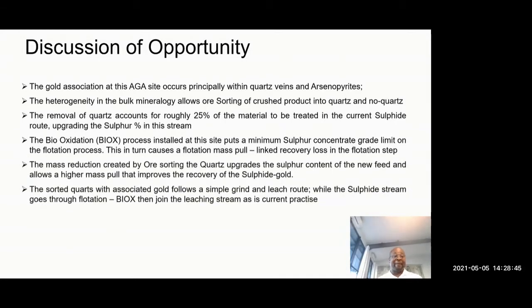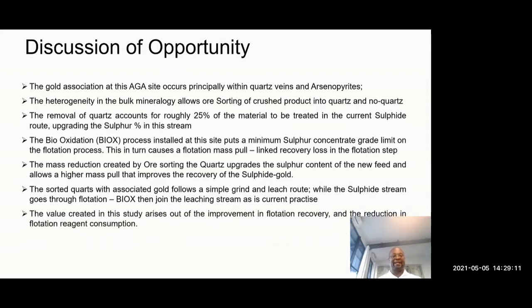So what are we doing? The mass reduction created by ore sorting the quartz upgrades the sulfur content of the feed and allows a higher mass pull. That improves the recovery of the sulfide gold. So the sorted quartz with associated gold follows a simple grind-leach route, like in the South African ore, while the sulfide stream goes through flotation and BIOX, then joins the leaching stream as is currently the case. And now the value created in this study arises out of improvement in flotation recovery and the reduction in flotation reagent consumption for the 25% that doesn't need to go through the complex circuit.